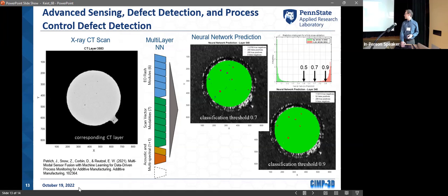When we go back to the neural network, we can actually predict those areas by taking these acoustic spectral data, the scan vector modifications. This is following the laser path, and also doing a camera, just a simple flash camera, and using that data and doing a neural network prediction of areas that are of concern. We can find out that we can map these areas pretty well from one area to the next in terms of predicting areas that may be of concern for the pores. The next question is, can we actually bring these in-situ data to actually try to correct these as well? Right now, we feel confident that we can find areas of problems that may be in the build, but the next step, of course, we want to actually actively repair these.